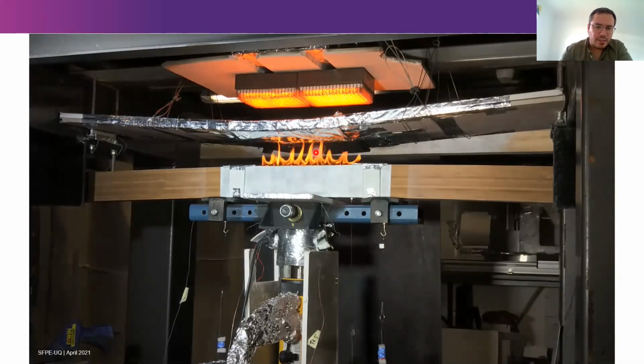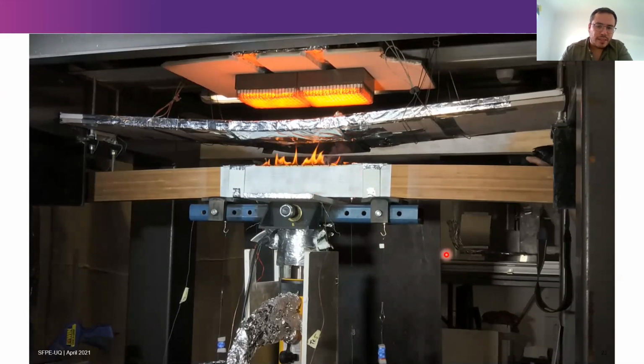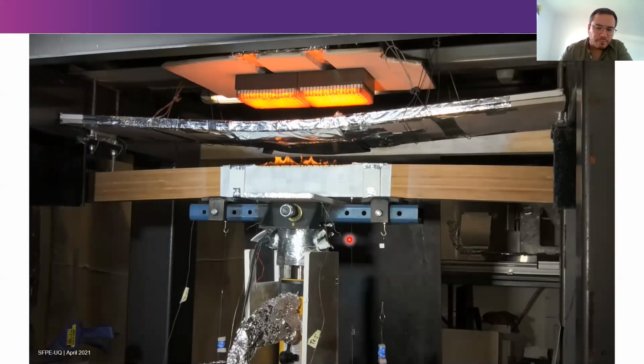Obviously, once the sample ignites and you start burning the specimen, the specimen starts getting more stress and more and more deformation until it finally reaches failure. We also used an electronic pressure valve that was controlling the pressure in the actuator and giving us feedback. So in order to maintain the desired stress level, we were always changing the pressure in the actuator to keep a constant pressure. And because of the temperature penetration and the burning of the sample, finally the sample ended up reaching failure at some point.